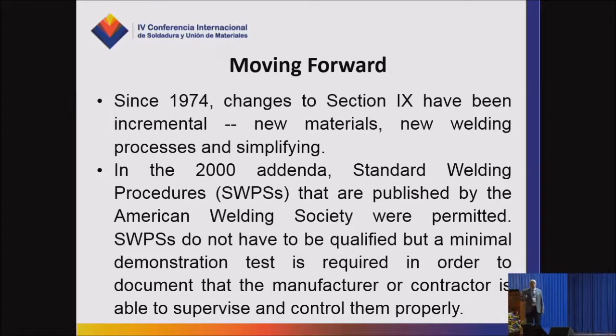So standard welding procedures cover material thicknesses from 1/8 of an inch up to 1.5 inches. Carbon steels in the as-welded and heat-treated condition. Stainless steels, as-welded condition. Stainless to carbon, as-welded condition. So if you're involved in construction where you need a welding procedure, the first place you should be looking is standard welding procedures.